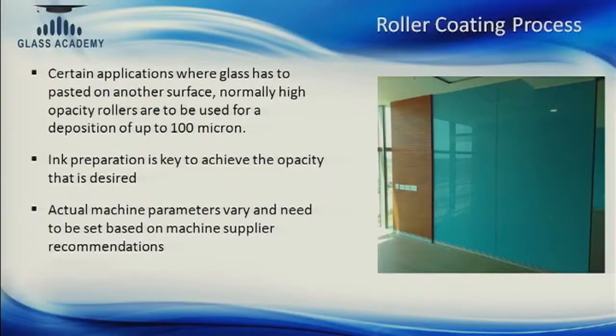So, for applications such as these where it is going on a wall, we recommend that you use a high opacity roller, go for a 100 micron deposition, and a viscosity of around 80 to 100, although parameters vary according to the inks that you use. And you can have a nice and even print where you cannot see the substrate while it is being pasted, which is the essential requirement for this process.